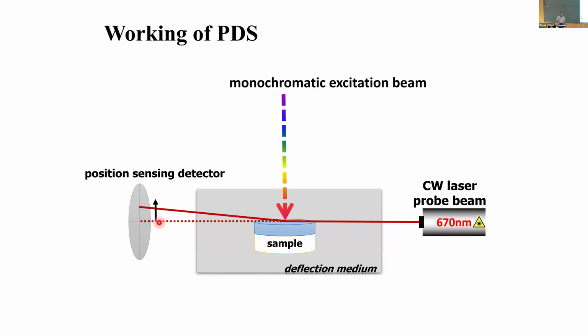Now, if you think of a typical absorption-based spectrometer, you're limited by the detector that you use. Basically, if you use silicon, you can measure from like UV up till around 1000 nanometers, and beyond 1000 you cannot measure. If you want to measure beyond 1000 nanometers, you have to use either lead sulfide or indium gallium arsenide detector, which can do up to maybe 1600, 2000. Beyond that, again, you have to change the detector to maybe germanium or some antimony based detector.